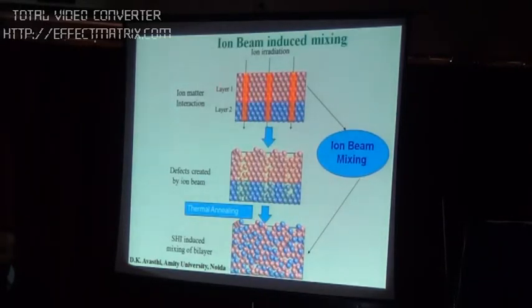You have one film here, one material, and another material. You shoot the ions here like this. It can produce defects. These were regular structures, but now there are a lot of defects here and a lot of defects here. Now when you anneal at higher temperature, they get mixed, so you get a mixed compound here. This is called ion beam induced mixing. It can also happen that just after this you go directly here. This is called ion beam mixing. So the difference is, if you get directly from here, it is ion beam mixing. When you go through annealing, it is ion beam induced mixing.